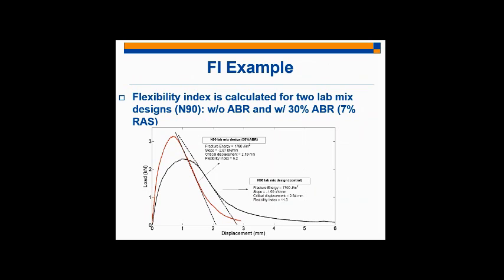So let's go back to the example that I showed earlier of the two load displacement curves of the two very different materials that were displaying basically identical fracture energy values. So you had 1780 joules per meter squared and 1790 joules per meter squared. When we run these numbers through the flexibility index expression that we proposed, you can see the huge distinction